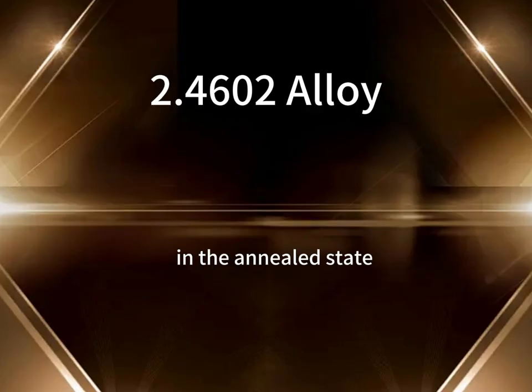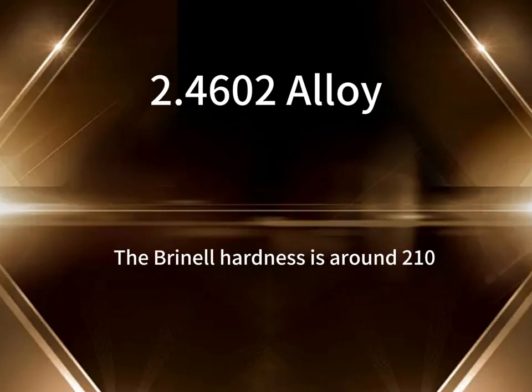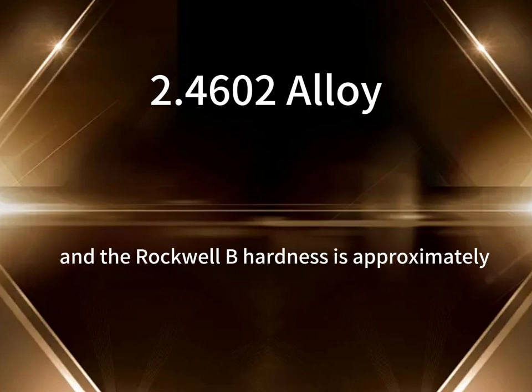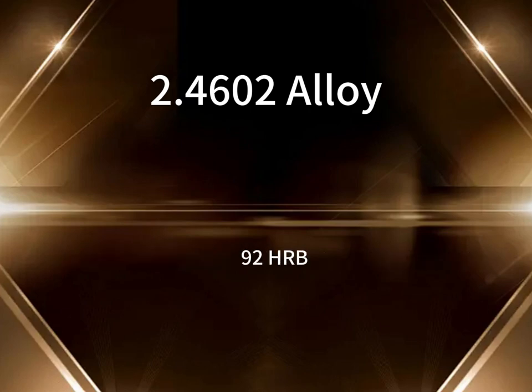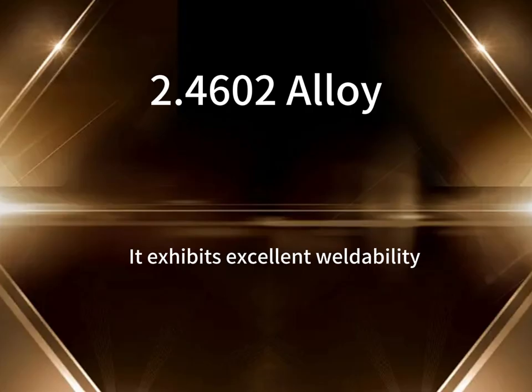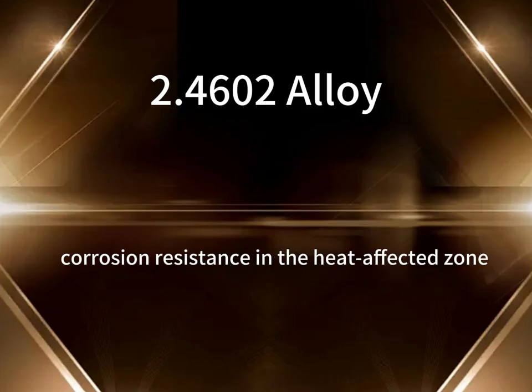Mechanically, in the annealed state, it has a tensile strength of greater than or equal to 690 MPa, a yield strength of greater than or equal to 310 MPa, and an elongation of greater than or equal to 40%. The Brinell hardness is around 210 HB, and the Rockwell B hardness is approximately 92 HRB. It exhibits excellent weldability, with no grain boundary sensitization, ensuring stable corrosion resistance in the heat-affected zone.